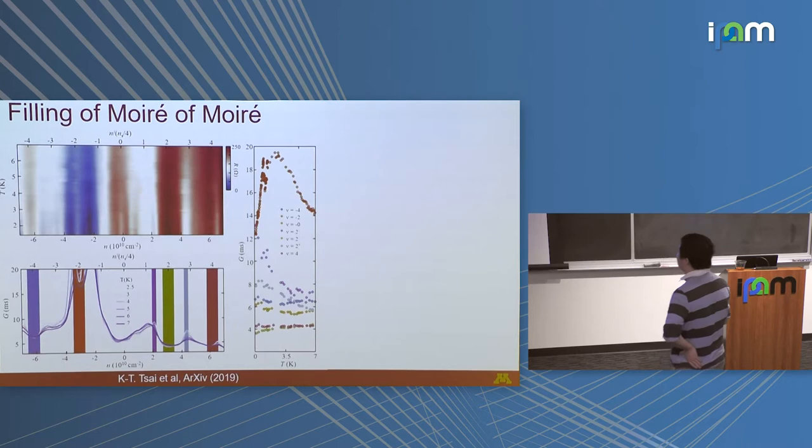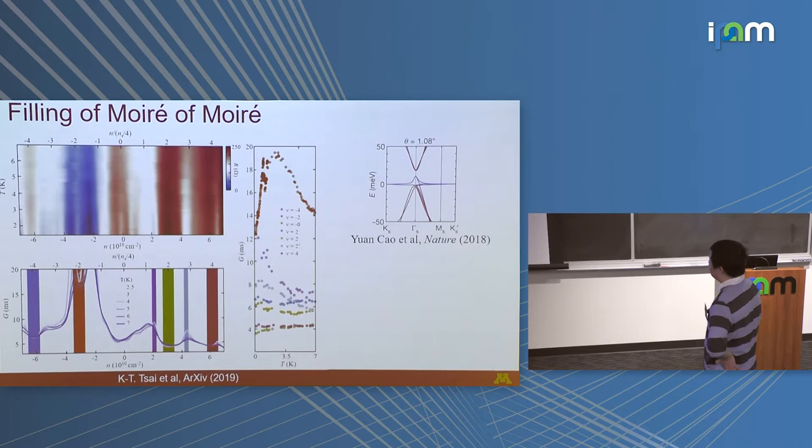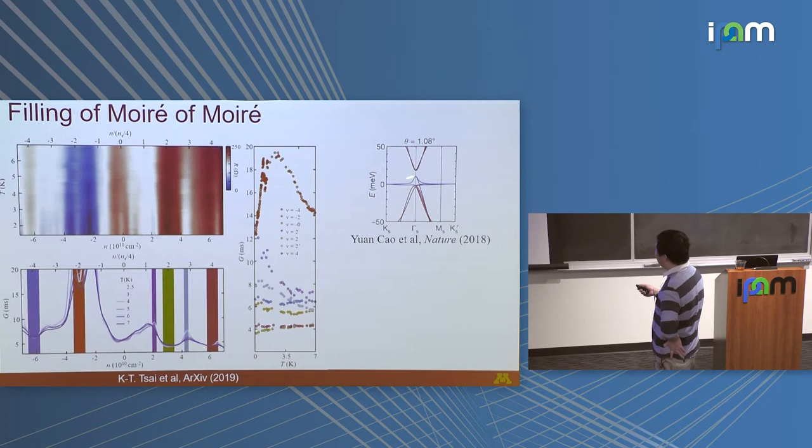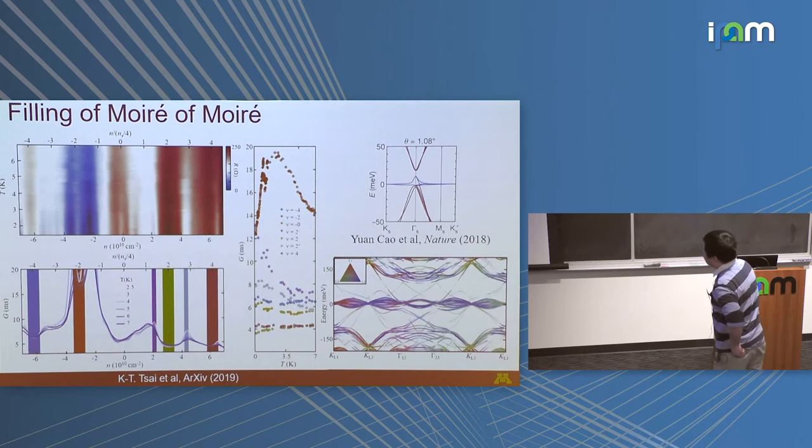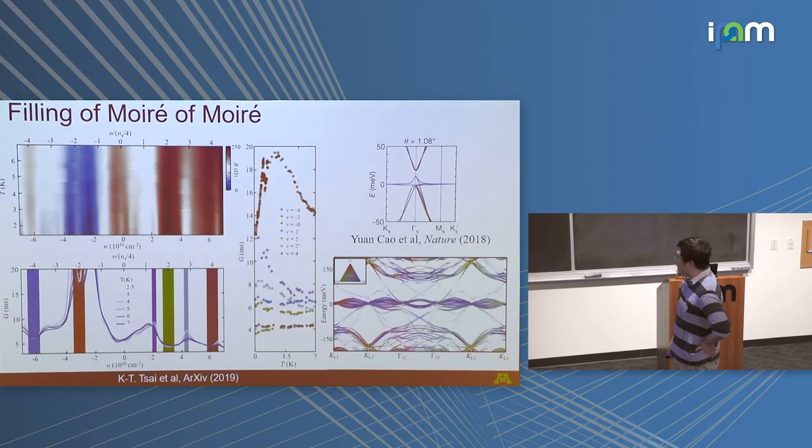And this is because the band structures of twisted bilayer and twisted trilayer are fundamentally different from each other. For twisted bilayer, you actually have a gap. So this is without relaxation, but if you include relaxation, you have a gap here as well. So you do expect to see an insulating case. But Zhou Yi, who is our collaborator from Tim Kaxiras's group, did this calculation for us for this continuous twisted trilayer graphene sample, and what they're showing, which is the most important part, is that you cannot get any insulating gap in between. So this is consistent.